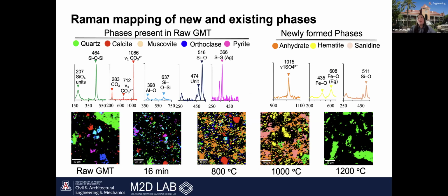And we were also able to compare their chemical phases with Raman spectroscopy. As I mentioned before, Raman spectroscopy helps us identify each mineral by its unique vibrational fingerprint. It allows us to see where different phases are located in the sample through Raman mapping. In this study, we used Raman spectroscopy to confirm the formation of new phases and to check which original phases remained after the activation. And the phase distribution map clearly shows the presence and the spatial distribution of these new and existing phases, such as anhydrite, hematite, and sanidine.